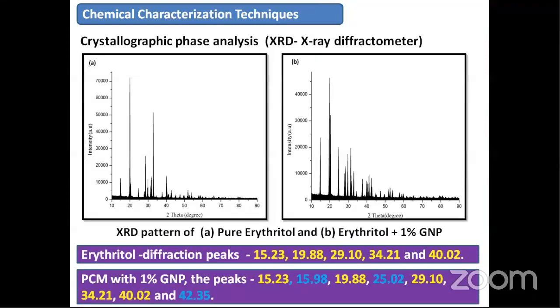X-ray diffraction spectra of pure erythritol and erythritol with 1% GNP are shown in the figure. The crystal size was calculated to be 35 nanometer and the lattice strain was 0.0062 for pure erythritol. It can be concluded that the addition of graphene to erythritol NDPCM has peak intensity approximately similar to erythritol, and it indicates graphene produced no crystal change in erythritol.